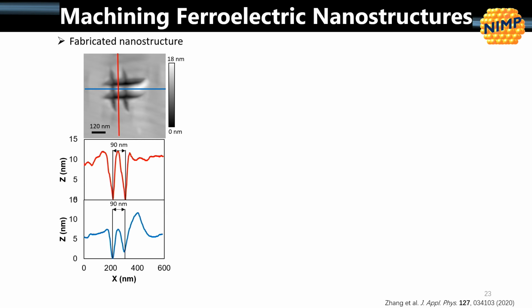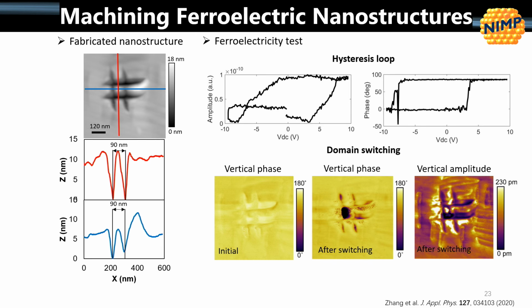You can see this kind of hashtag, which of course is carved by rotating the sample and locating the spot again. With a stiffer tip, you wouldn't need to do that to have the same structure. And fortunately, it remained ferroelectric. It still switched. Maybe the hysteresis loop doesn't look as nice, but we were able to switch it as though it retained the ferroelectricity.